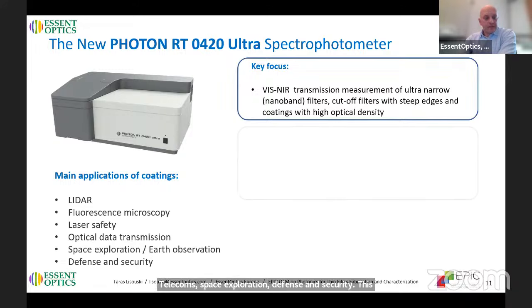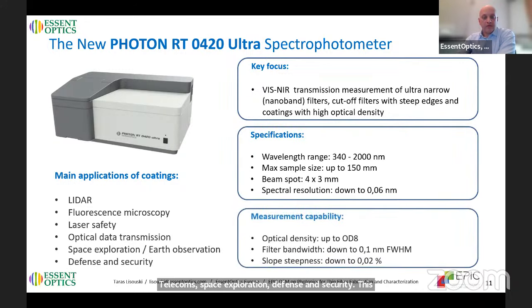This is a broadband tabletop system with a very wide range, with an extremely high spectral resolution down to 0.06 nanometers. We are capable of measuring optical density up to OD8. Filter bandwidth can be as small as 0.1 nanometer, and slope steepness can be as small as 0.02%.